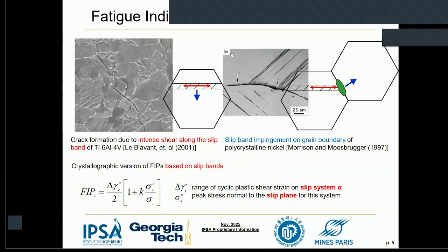Well, we know that the fatigue crack initiation is induced by different micromechanisms, such as slip bands in the grains, or the grain boundaries. So different micromechanisms will lead to different fatigue crack initiation. Here I just take a very typical one, which is often used for titanium.